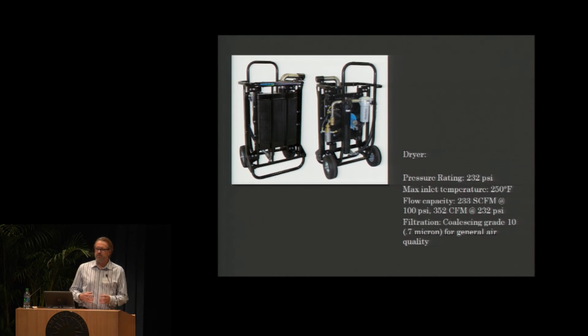Compressors are basically heat generators, and as they compress air, they generate heat. Heat condensates. The problem with, and we've heard this before in the talk, is that dry ice doesn't like water. You have to get rid of the water out of the system. We use a pretty large dryer, and this is about 25 feet away from the compressor. That allows the air to cool down before it hits the dryer. The dryer essentially separates the water. The clean, dry air is now sent to the blasting machine. This is absolutely vital. If you don't have this, basically you get clumping, it'll be very hard in operation, and we've heard what water does to CO2 before.